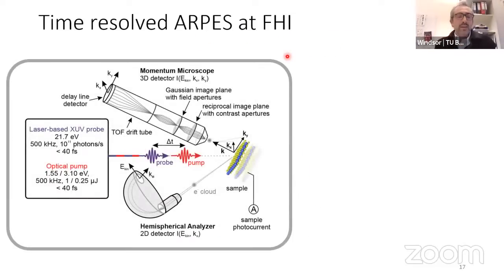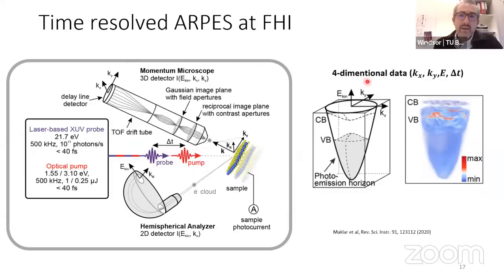This is a conceptual description of the time-resolved ARPES setup at the Fritz Haber Institute, where the experiment I will describe was used. The kind of data you get out of this is very nice. It's four-dimensional: two dimensions of momentum, one of energy, and the time delay, which is the delay between the pump and the probe, before photoemission to one of these two detectors. And this is the kind of data you get out. It's very pretty. If I'm not mistaken, this is data from tungsten diselenide, a TMDC.